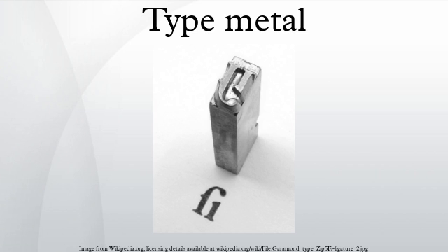Repeated assays were done at regular intervals to monitor the alloy used, since every time the metal is recycled, roughly 0.5% of tin content is lost through oxidation. These oxides are removed with the dross while cleaning the surface of the molten metal. Nowadays this battle has lost its importance, at least for monotype. The quality of the produced type is far more important.